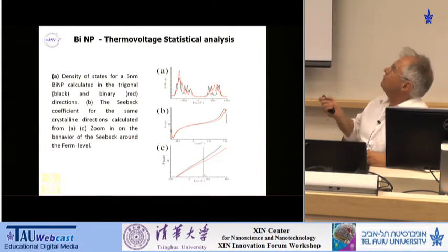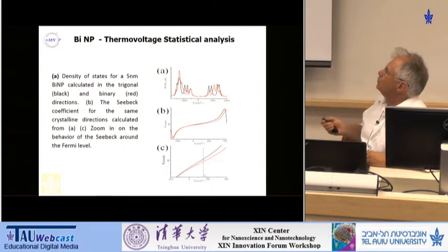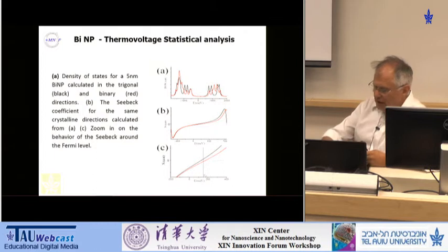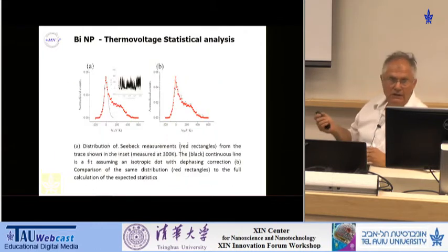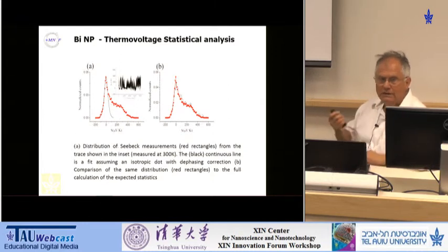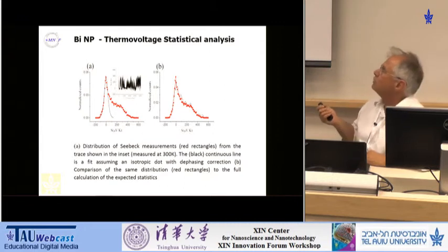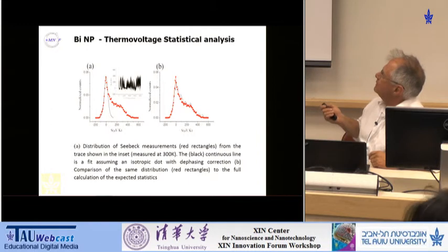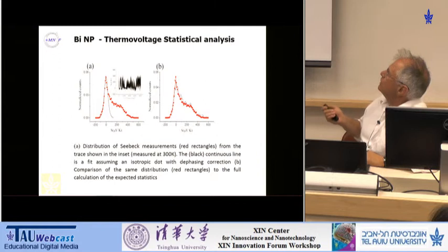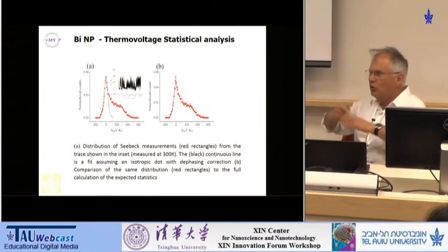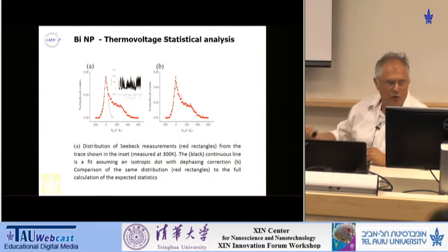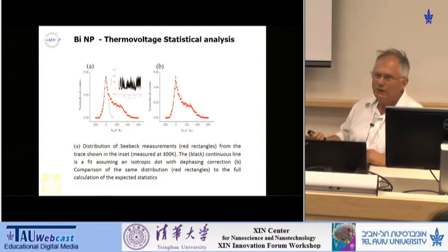And what we have seen that if one formulates the theoretical properties of those particles into the 2 different directions, indeed one could see different value of thermovoltages. And in other words, what we see here is actually a single nanoparticle which changes simultaneously its direction of crystal in a spontaneous way in every conceivable angle. Because if we compare our experimental results, those are the red dots here or triangles, with the theoretical simulation, that should be the measurement of the thermovoltage, the distribution over all crystal direction, rather than a single nanoparticle with a single value of thermovoltage. What we have here is sort of thermodynamic ensemble of nanoparticles in one.